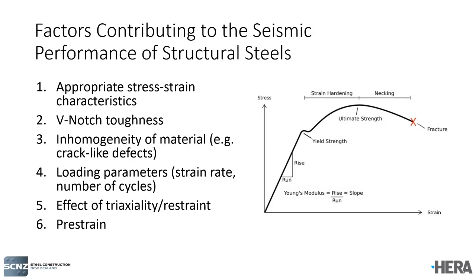Also, the loading parameters have an impact on the seismic performance of steel. The rate at which the structure is loaded has an impact, and also the number of cycles of inelastic demand. Another factor that can contribute to the seismic performance of steel is the presence of triaxial restraints. If you have a very complex three-dimensional joint and the steel is essentially constrained from deforming, it will end up behaving with a very limited ability to deform plastically.